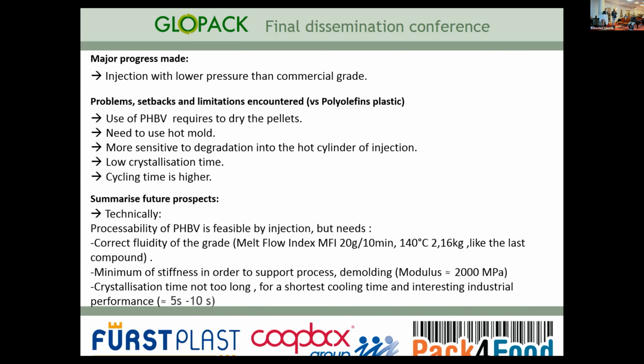So to summarize, technically, processability of PHBV is feasible by injection, but for that we need a correct fluidity of the grade. So the melt flow index needs to be as the last compound we tested, for example, because the pressure is a good value. We need to have a minimum stiffness in order to support the process, because we need that for good demolding. We can have an objective of flexural modulus of 2000 MPa. And we need to have a crystallization time not too long for the shortest cooling time and an interesting industrial performance, of course.